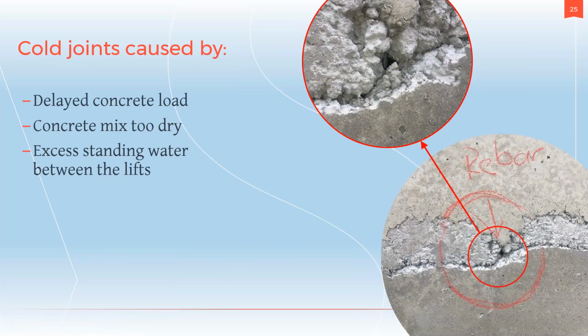I'm going to start off with cold joints, which are a bit difficult to detect using non-destructive evaluation. This cold joint here was on the side of a 5-foot thick slab, which was the roof of a radiation room in a hospital. So we can see it at least partially from the side. But the slab was quite large, about 80 foot by 30 foot. To remove and replace the whole thing would have been really expensive. So we needed to use something like non-destructive evaluation to tell us exactly how far the cold joint extended, so we could figure out reasonably how much removal was actually needed.